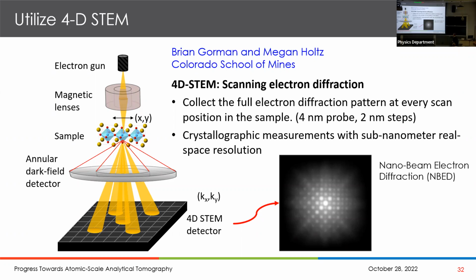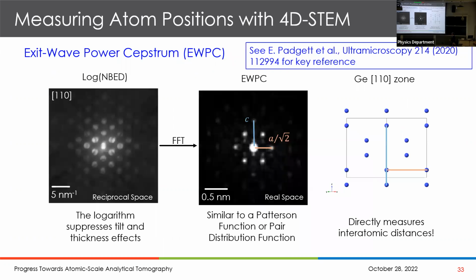If you record that in a pixelated STEM detector, not just simply something with an annular symmetry, but pixelated, as you can see, even the individual pixels in this. Then you can start to use that as a coherent diffractive imaging approach and reconstruct the image with those types of approaches. And I'm not going to go into coherent diffractive imaging, but I go into this a little bit more. And in particular, this is a very nice paper by Padgett et al. This is from the Cornell group, very recent, where they look at coherent diffractive imaging using exit-wave power cepstrum.